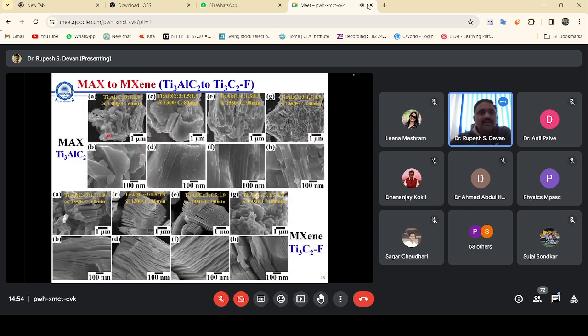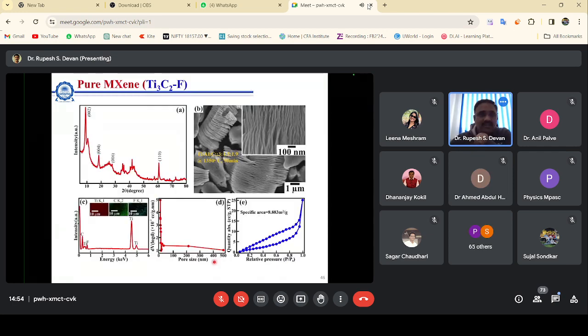So you can see here, the MAX phase at different reaction parameters forming a layer by layer structure. And when you etch out aluminum from this, then slicing has been done and the separate layers are being observed. So this has a very good energy storage mechanism as well. So once MXene has been formed, you can see the surface area has drastically increased like graphene. And then you can see here this XRD shows a perfect crystalline morphology.